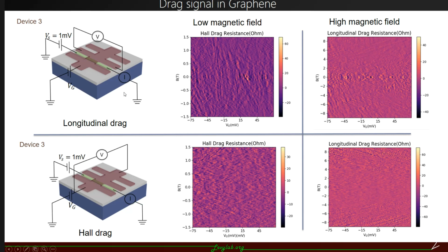In the longitudinal drag, the drag voltage is measured parallel to the driving current. So here the main feature is at low magnetic field in this longitudinal direction. And in the Hall drag, the drag voltage is measured perpendicular to the direction of the running current. In this configuration, the main feature is not at low magnetic field, but instead it shows up at high magnetic field. It has this kind of stripe-like features.